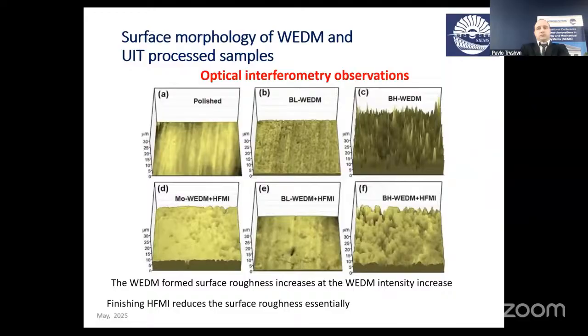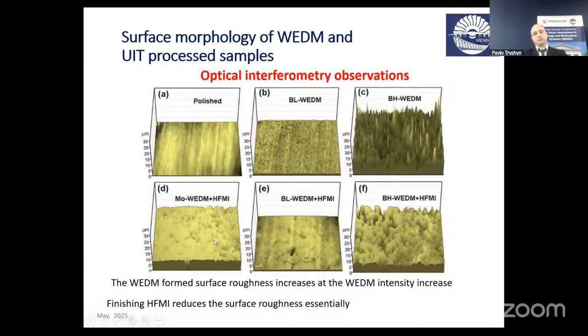Considering the surface morphology of the samples after wire electrical discharge machining (WEDM) and following a high-frequency mechanical process, we can conclude that in comparison with the polished sample, the surfaces after the EDM process became much rougher. So the higher the energy used, the larger the surface roughness. Fortunately, finishing surface modification by high-frequency mechanical impact (HFMI) allows us to significantly reduce the surface roughness.